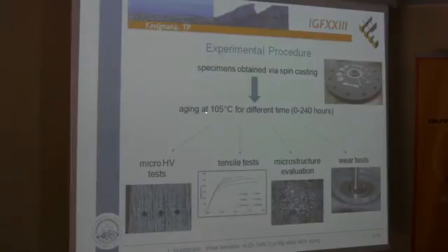We aged all the samples at 105 degrees for different times, starting from 0 hours, the not aged sample, up to 240 hours. The temperature of 105 degrees was chosen because this temperature is a reference for the traditional zinc alloys, because the properties that the material reaches after 1 year of natural aging can be reached also after 24 hours of aging at 105.